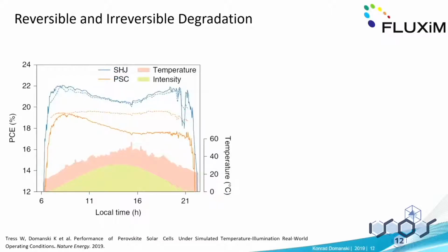So let's have a look at one day. I just chose one day, the temperature and illumination profile for both devices. And what you can see here, the orange curve is perovskite, the blue one is silicon heterojunction. The broken curves are what we would predict the efficiency to be at any given moment of the day, again, from this pre-characterization colorful graph that I just showed you. And the solid line is what we actually got. So we see that for perovskite, we developed this discrepancy towards the end of the day. This is the reversible degradation that we see kicking in.